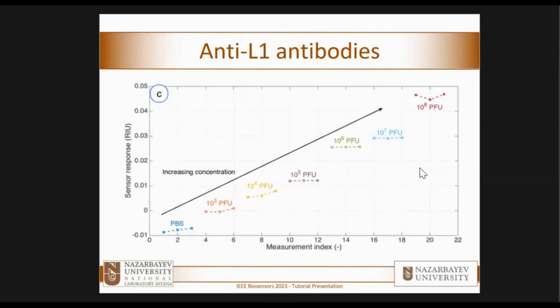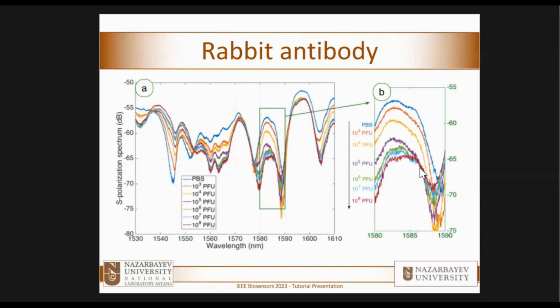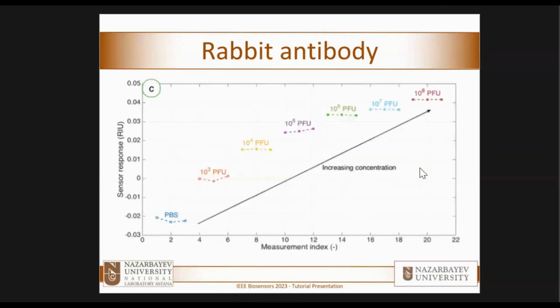And that's actually how the dynamics of detection works. The data are sampled every 3 minutes. So notice that the response is quite staircase. So that means that after reaching a certain concentration, the system remains stable. And when detecting the next one, the system changes quite rapidly. And that's how it works with the other type of antibody. So again, the spectra are quite random. We select one part to analyze the data. And when we point it out here, we have again a decrease in the spectrum. This time is even larger because the sensor has a larger sensitivity. And again, we have a detection here. So yes, the sensor sees the virus. That's a quite reliable result.